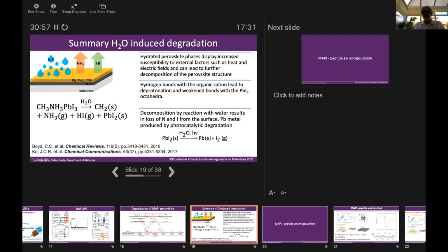So we find that the overall process is a decomposition by reaction with water, which results in the loss of nitrogen as ammonia, and iodine probably as HI, but we're also losing some iodine due to photocatalytic degradation of this lead iodide. So the photons coming from the X-ray source seem to also lead to formation of lead and iodine. This is unlikely to happen in a solar cell material, but obviously it does in our XPS instrument.